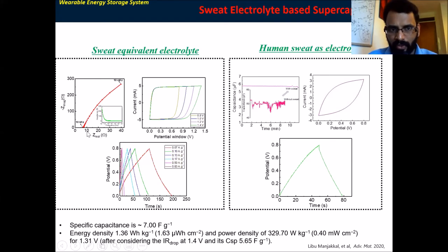You can see that in impedance spectroscopic analysis, the solution resistance is less than 10 ohm, and the diffusion in the high frequency range, as in the low frequency range also, the resistance is around 40 ohm, and the capacitive impedance is 300 ohm. So the resistance is very low, and you can see here the different voltages in a sweat equivalent solution, how the cyclic voltammetry is almost a rectangular shape, but depending on the scan rate. Normally when we are doing the cyclic voltammetric analysis, we need to scan the device from a very low scan rate, because then you can see how the material or the ions diffuse into the bulk of the material and a full chemical reaction. So in such a reaction, you can see it's a quasi-rectangular shape, and in the paper I explained that it is due to this redox reaction.